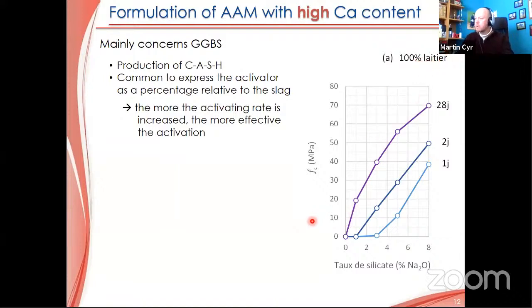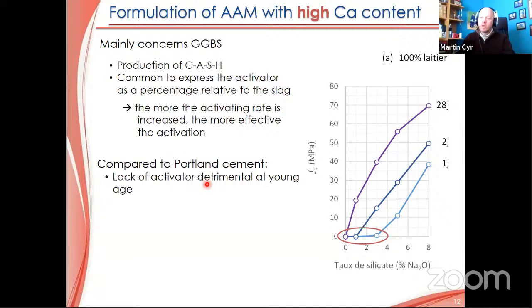Sorry again for the lack of translation. The compressive strength at 1, 2, and 28 days against the silicate amount expressed in terms of sodium. And we can see some small things when we compare it to Portland cement. Sometimes the lack of activator is not very good at young age. We can see here at 1 day, if we don't put enough activator inside, we will not have enough strength for demolding. We will have something much better if we put more activator, but the price is increasing.